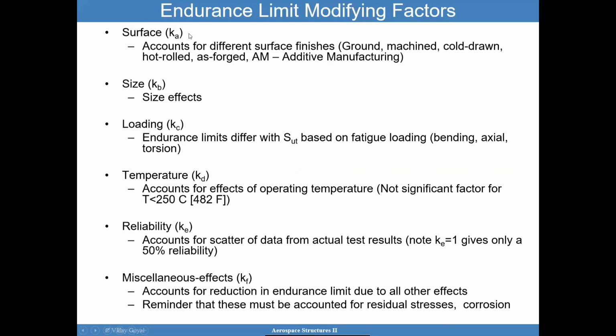So the surface finish, Ka will consider the surface finishes, whether it's ground, machined, cold drawn, additive manufactured, Kb is the size factor. Kc is basically bending, axial, torsion corrections. There's not always a Kd here for temperature, but sometimes there is. If you're looking at reliability of 50%, just use Ke of 1. And then miscellaneous effects, we'll consider other stuff like corrosion and stuff like that. But that's hard. You have to basically test stuff with corrosion to figure out what the knockdown factor is.